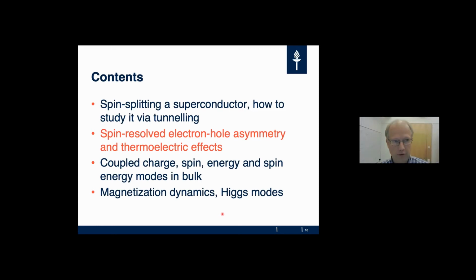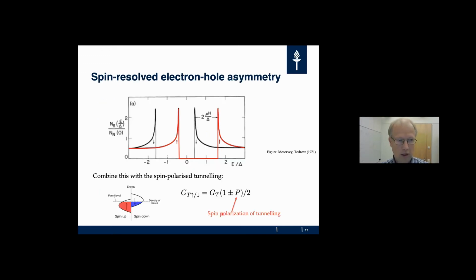Okay, so this was the sort of easiest tunneling experiments on spin split superconductors. Now I would like to point out one point here related with the asymmetry of these peaks. So the density of states that I just showed contained these peaks which were split by the exchange field. This picture is from the first experiments by Meservey and Tedrow on this effect.